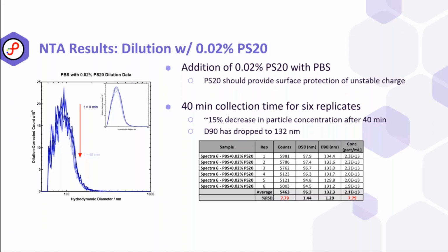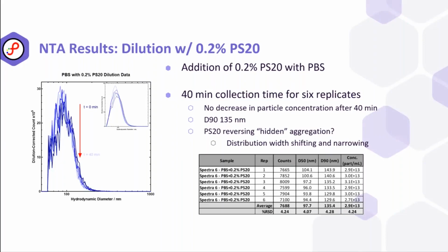But what we're not seeing is that 50% decrease. It's really considerably lower. And also we note that the D90s dropped to about 132 nanometers. So there's something else going on here. And I think in the highest concentration surfactant data, we can kind of start to see what that is.